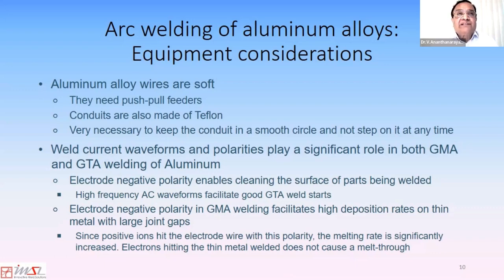The oxide has a very high affinity for absorbing water. And if it's a rainy area in a city like Mumbai and you have aluminum oxide on the surface, you can bet that the weld would have quite a bit of porosity. And how to deal with these are some of the issues that are discussed here.